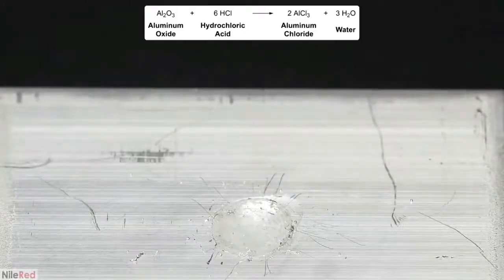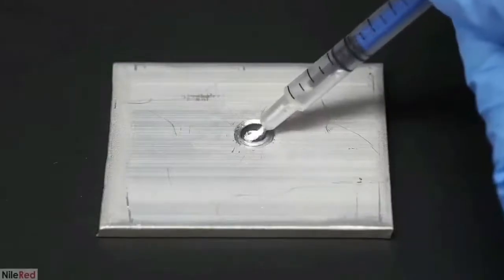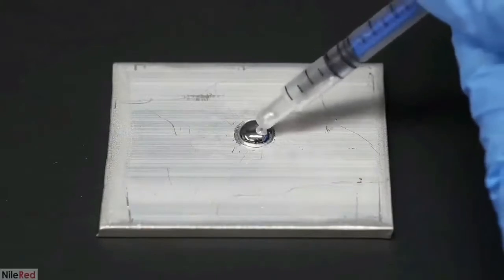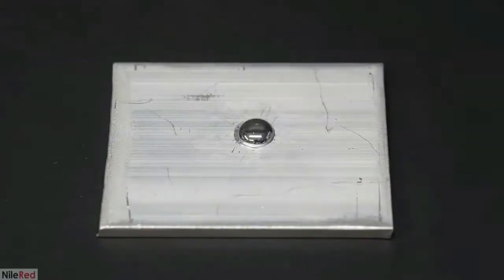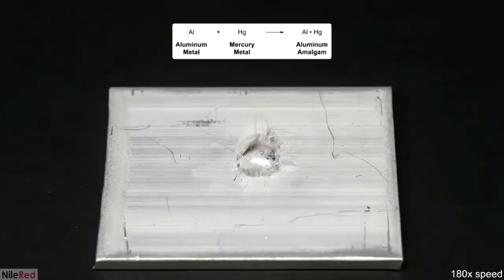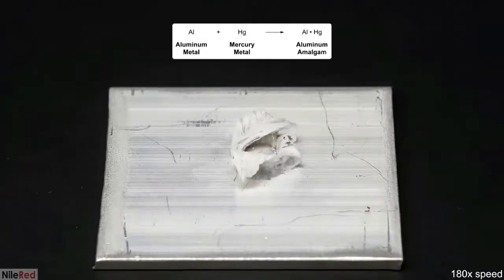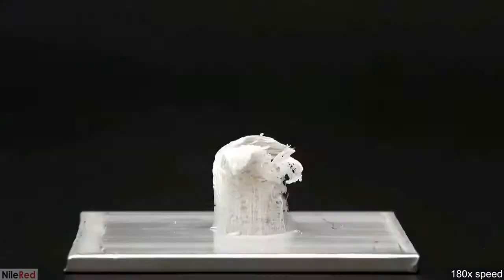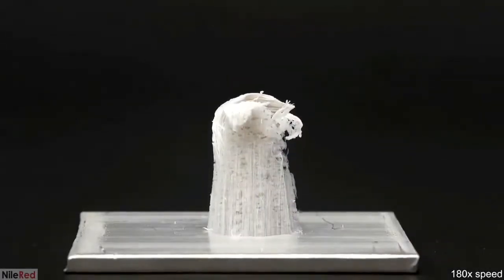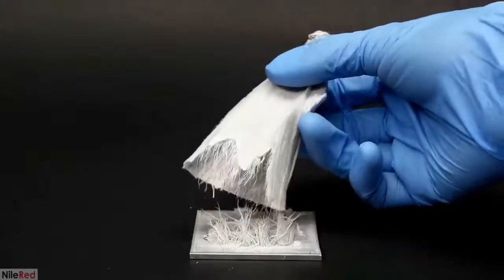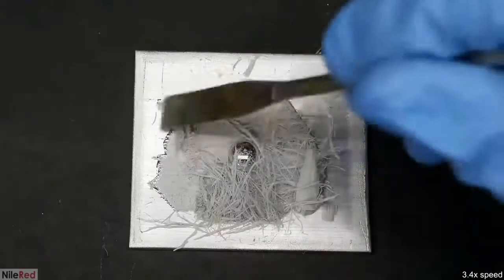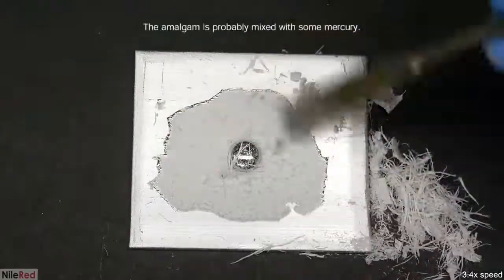In this case we add hydrochloric acid on it, and the hydrochloric acid will react with aluminium oxide to form aluminium chloride and water. So right now the aluminium is free to react with the mercury to form the amalgam. Let's watch this short video to see what the amalgamation of aluminium looks like. In the end, you can see the result will turn out as surface etching and pitting and also loss of mechanical strength in aluminium.